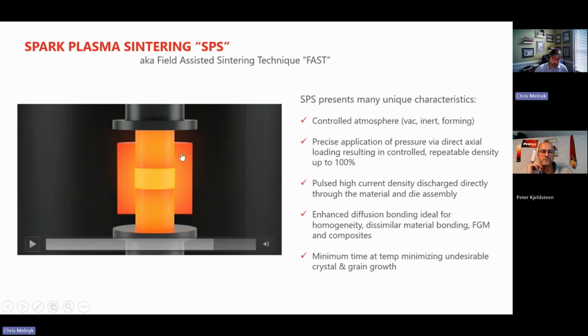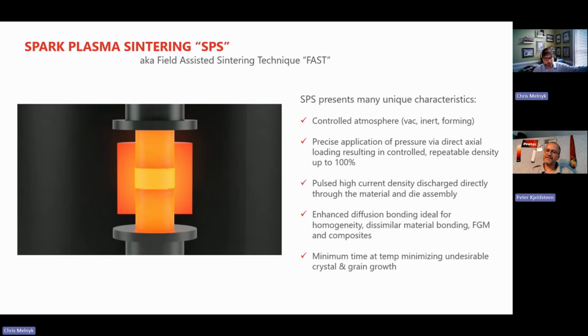And then sometimes it's a hybrid, because in some cases, like aluminum oxide being a good example, it becomes more conductive as it gets hotter. So its conductivity starts off as an insulator, and then as you heat it, it'll start to absorb some of that current density through it as well. So in that case, it is the die, but it's still an intimate contact with the part.